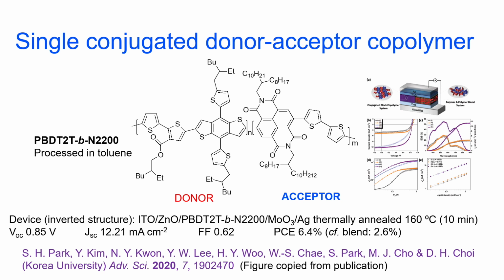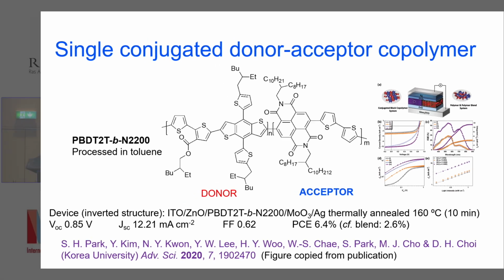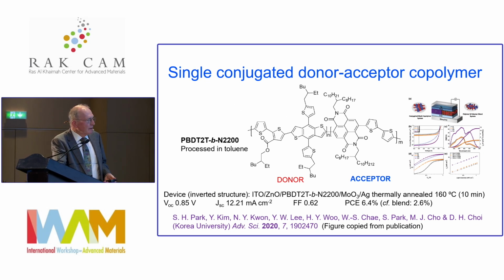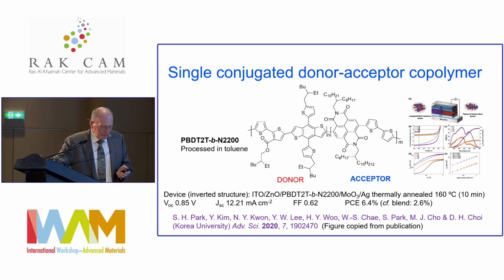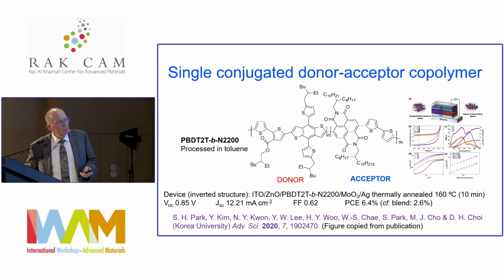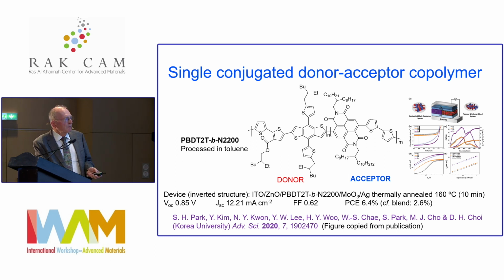driving force in this area is, can we make a polymer which is a combination of the donor and the acceptor all in one block copolymer? And here's an example of that. And this is a Korea University contribution. And you'll see the privileged groups are the same as the ones we've talked about, the left and right, but the donor block copolymer, the N repeat units, and the M repeat units on the right, the acceptor, all in the same material, and the device efficiency of 6.4%, which is about the best I think it's ever been reported for that kind of approach.